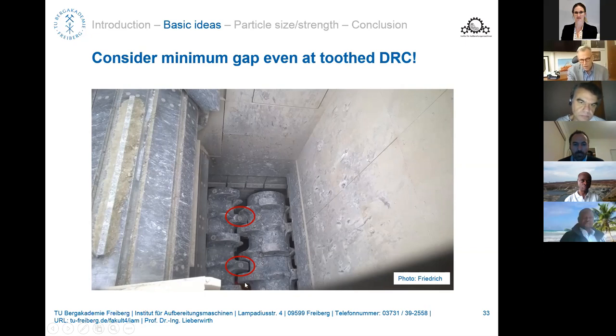When I looked into the crushing gap, I found the crusher had been operating for about a year by then. The material was not very abrasive, like a limestone, quite competent, but not very abrasive. What you can see here is a crushing gap. Now think about where the material could escape. It was very clear, and the wear on the teeth was not at the tip of the teeth. The wear was on the rear side, on the back side of the teeth. You can see very nicely shiny parts on the other side as well. So essentially the material was squeezed here and didn't have the chance to escape, and that's why you produced extraordinary forces on the machine. These forces led to the oscillations which finally brought several parts to fall apart in the steel structure, because simply the forces were too high.